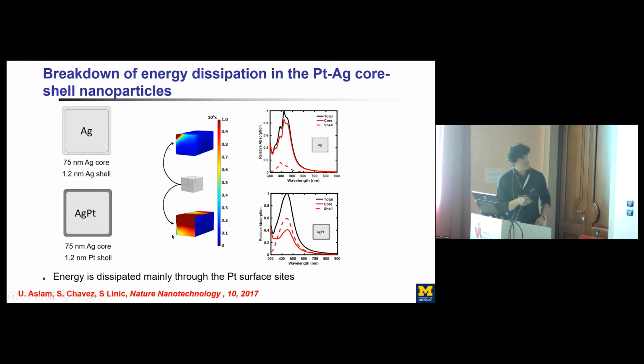And basically the bottom line is that as you deposit platinum on this surface, it exactly starts acting the way that I just described, where you have this antenna effect of silver, and then you have this platinum here, where most of that energy is dissipated through the platinum. So you get high field, you put platinum in, it has allowed electronic excitations, and then energy preferentially goes to that platinum, and you can get enhancements compared to having a pure platinum shell or having just silver.